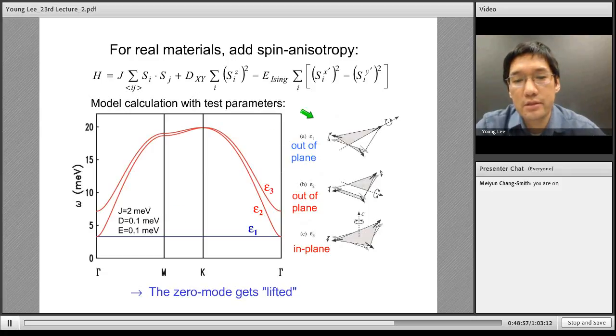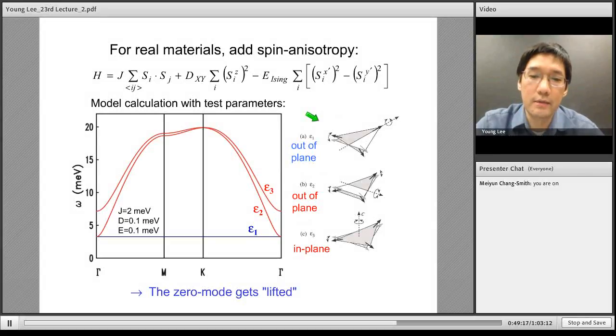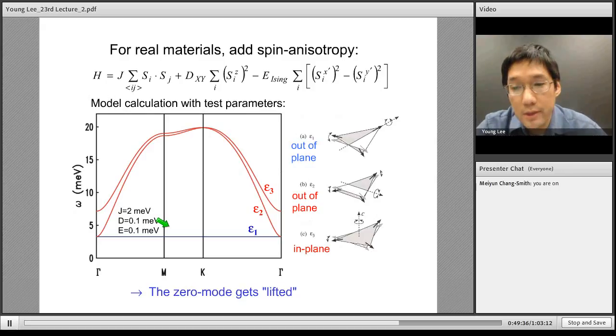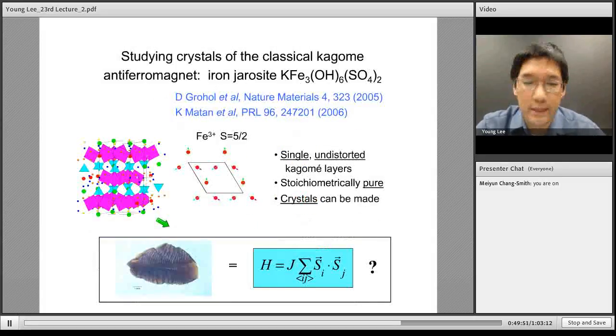And one way to think about that is to think about the polarization associated with this zero energy mode. The physical picture I showed in the previous slide was that you're taking a rotation axis along one of the spins on a plaquette, and the other two are rotating in opposite senses, like shown in this top picture. And this type of excitation wants to pull the spins out of the Kagome plane, so this has an out-of-plane energy cost, and every spin along that line has to pay that cost. So you do raise your zero energy mode to some finite energy, but it does remain flat still. So that's where this lifting of the zero energy mode comes from, and the energy gap will be related to the XY-like anisotropy.